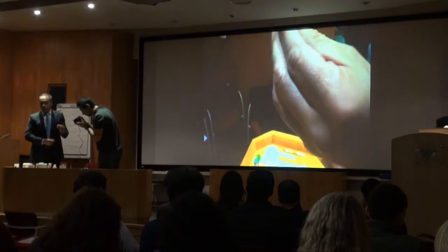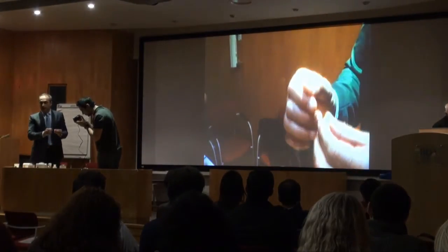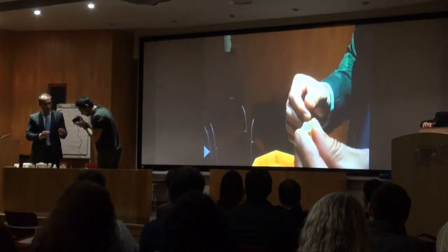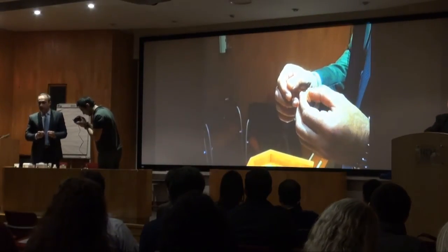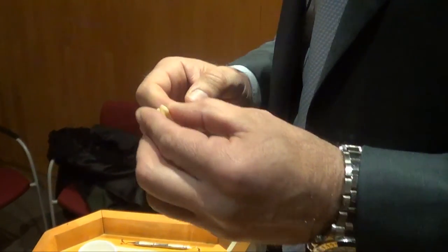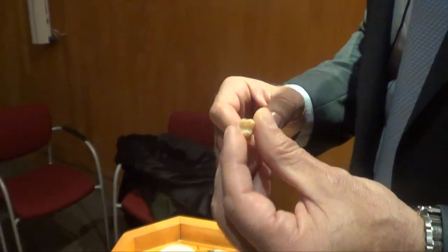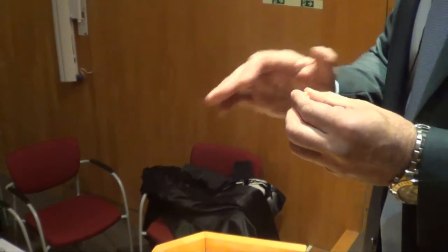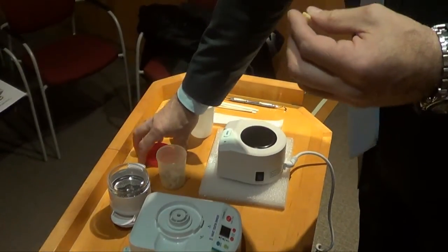So after mechanical preparation, we clean it with a tungsten carbide bur and not a diamond bur, for a very simple reason: the diamond produces heating and can damage the collagen which is inside. The tungsten carbide bur is chipping, just cutting the unnecessary material, any epithelium and soft tissue remaining.